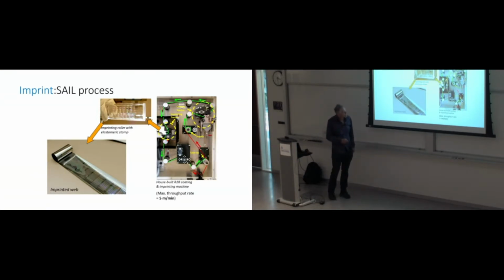And then this is a 4-inch sample with the aluminized mylar. It actually has sputtered stainless steel on the back, partly for static buildup in this case. And then this is the imprinted pattern. Now, if you just want to goof around with stuff, you can make a pattern, and we just had an imprint come down, and we just had an air bladder that provided the force, and it kind of starts from the center and squeezes things out from the center.